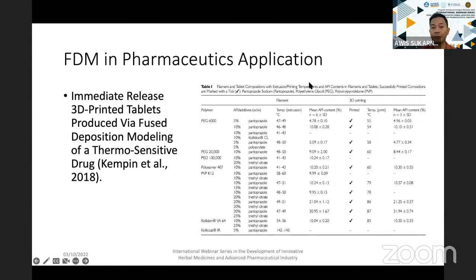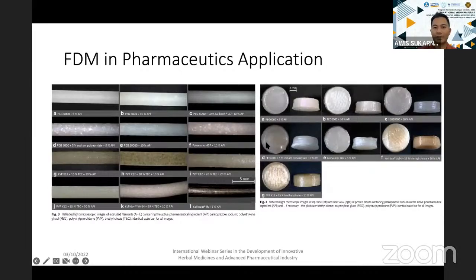low degradation point. As you can see here, the filament that they use, this is the polymer that you use for the extrusion, and they use polymers that have a very low transition temperature here. You can see here, roughly between 40 up to 60-ish, and this one is just a control. So they decided to use one with the higher melting point here. This one is the highest one, 142 to 145, and the rest are below 60 degrees Celsius. So it means, let's say the degradation point of the API is low, then you can use this material. And then after that, they managed to extrude most of the filament here.